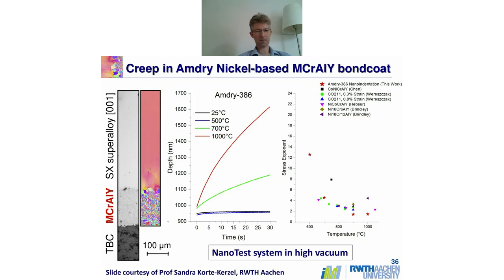And this is a similar sort of thing now. This is higher temperature work on a bond coat from a thermal barrier system. So we looked earlier at the thermal barrier coating system. I talked about how we were able to protect this nickel-based superalloy substrate from the very high temperatures. And in between the two things, we have a bond coat system to make sure that there's decent bonding. And this MCrAlY bond coat's mechanical properties also need to be optimized at high temperature.